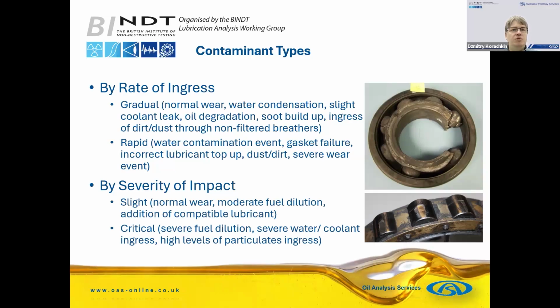And then we can look at it by severity of impact. There is some contamination which is going to have moderate impact, slight impact. So things like normal wear, it will build up. It may start becoming a problem by itself, but it will take time. A moderate fuel dilution, we're detecting a contaminant, but it's not causing a problem yet. It's very gradual ingress of fuel, for example, gradual buildup, or addition of a lubricant that's actually a compatible lubricant can work with a lubricant that's already in the system, and we may detect it and we may decide actually we know that it's okay, or we may perform a compatibility study and confirm that it is okay so that we are sure, and then carry on.